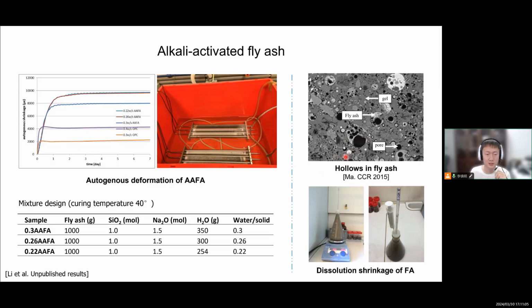It's actually very considerable. So that means that even though there is early age chemical shrinkage or autogenous shrinkage, it is not an indication of self-desiccation or consumption of water. So we need to focus on the later age. And why the expansion part is not so apparent, just a little bit of trend, I think is also related to the voids, because they provide space for the formation of reaction products. So they can form here, which means they will not cause expansion of the whole system.